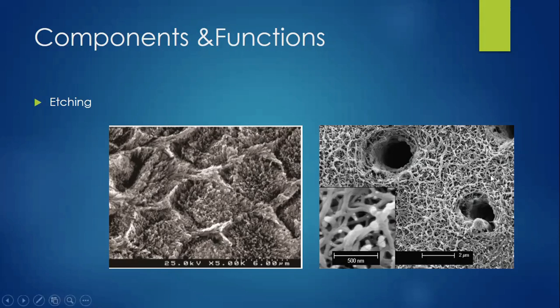So it completely removes the smear layer and opens the dentinal tubules in a funnel shape, creating a collagen mesh into which the resin can penetrate. This exposed collagen acts like a mesh and creates nanometric spaces of around 10 to 40 nanometers. After this etching process, around 70% of the volume is water dispersed around the 30% of collagen fibrils that remain anchored to the subjacent mineralized dentin. So demineralized dentin is a hydrophilic substrate, which is very difficult to manipulate clinically, because we know resin has a hydrophobic behavior.